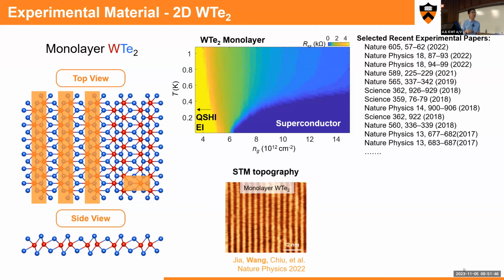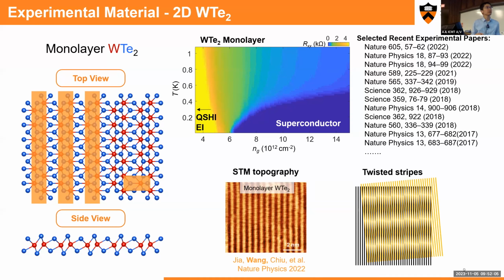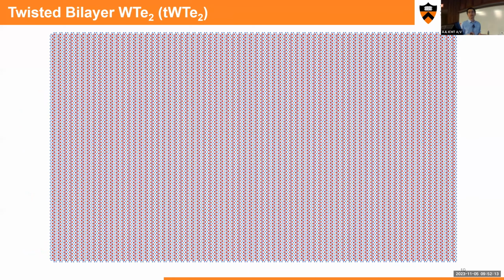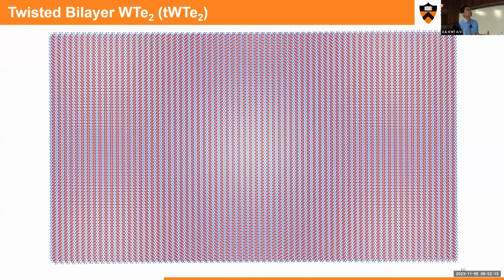In an STM study recently, we collaborated with Ali Yazdani. We found that the topography and the conductance of the tunneling current actually show stripes. This is because the tungsten atoms and tellurium atoms get pushed up like this. If you twist it, this is the situation we are going to see. I'm going to show you what the Moiré lattice looks like. So this is tungsten ditelluride, and then we twist it by some angle.